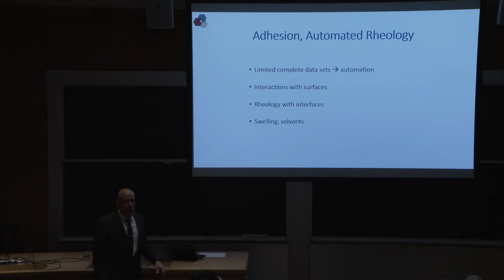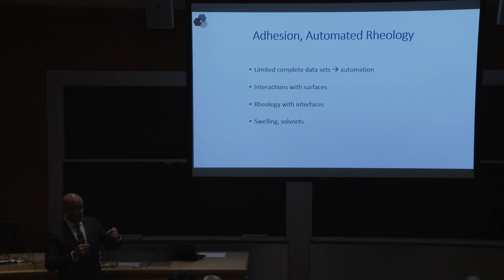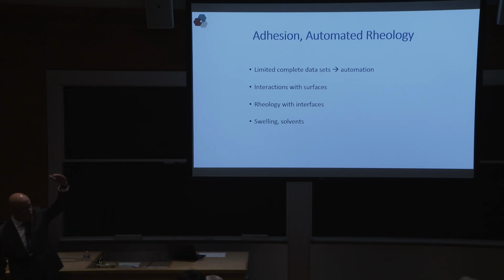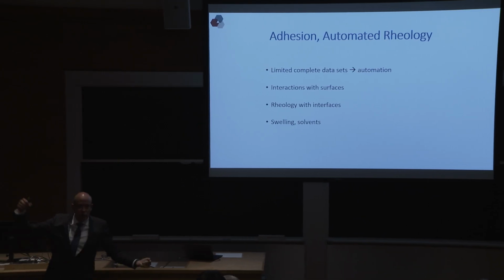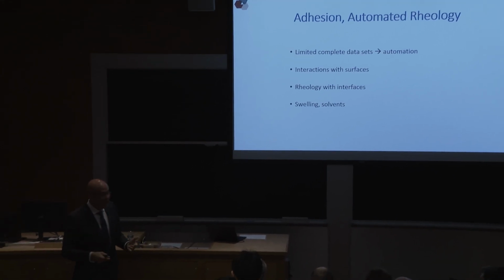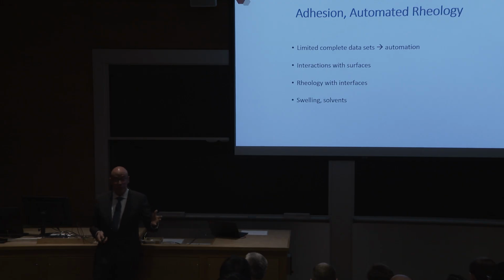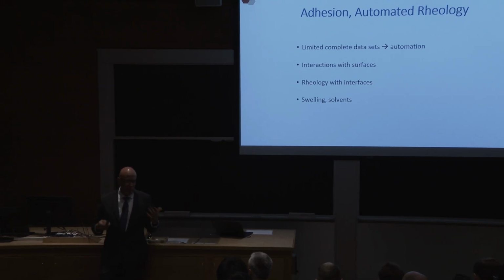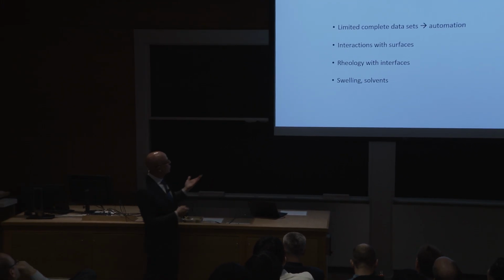Okay. Now, the biggest challenge that we face in all this work is generating new data for new polymeric materials. And anybody who's measured a viscosity or a rheology curve, et cetera, for a polymer knows that it is a very painful process. They make very big samples. Sometimes they cut it in this dog bone shape, and they walk it to a huge instrument this size that destroys the sample, and you do it again and again and again. And we need to do it about 10,000 times to generate this data. So the problem is a bit intractable, right? So how do you automate all of that?